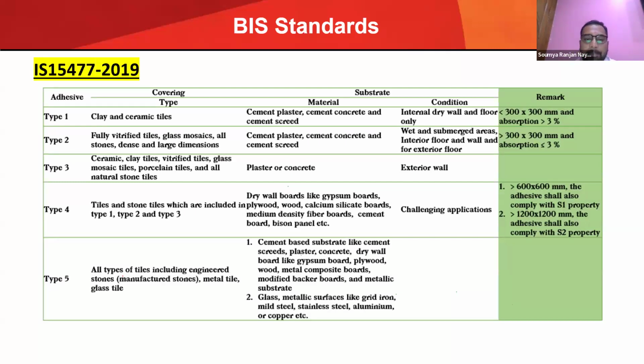Then type 5. From type 1 till type 4, all these adhesives are meant for cement and dry substrates. But type 5 is meant for wooden, metal, plyboard, all kinds of aluminum, stainless steel, mild steel, like in lift areas. In some constructions, we use steel staircases. If you want to fix tiles or stone on a steel staircase or a metal staircase, we have to use type 5 tile adhesive.